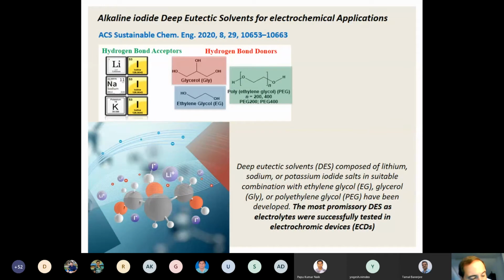Okay, and looking for this kind of applications, deep eutectic solvents are very interesting for electrochromism, but also for other energy applications. And recently, and this is very recent work, we developed alkaline iodide deep eutectic solvents, in particular using hydrogen bond acceptors, lithium iodide, sodium iodide, potassium iodide, in combination with hydrogen bond donors like glycerol, ethylene glycol, and polyethylene glycol. And these deep eutectic solvents are very promising as electrolytes. They are very interesting for electrochromic devices, but also for other applications like solar cells, and this is something that we are working on now. And this was published very recently in ACS Sustainable Chemistry and Engineering.